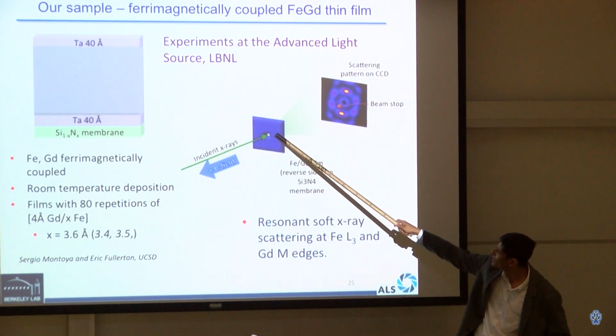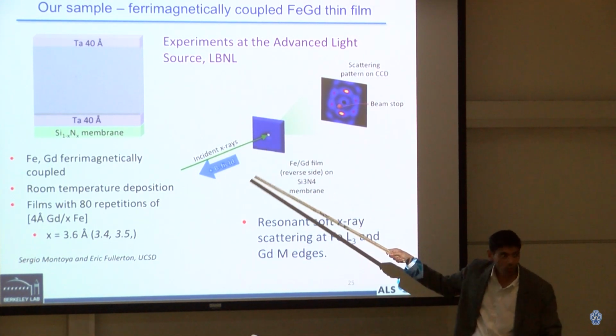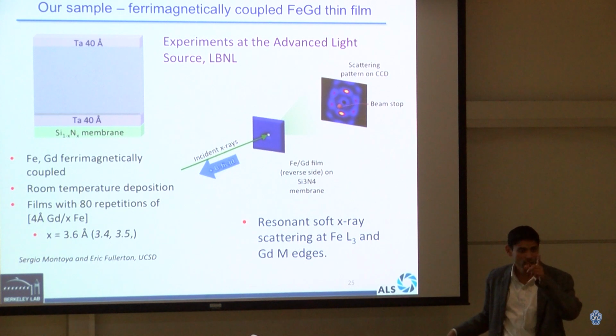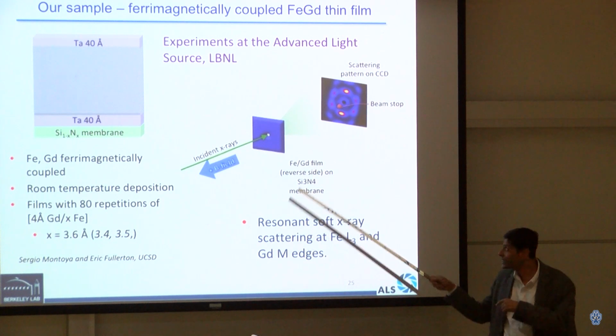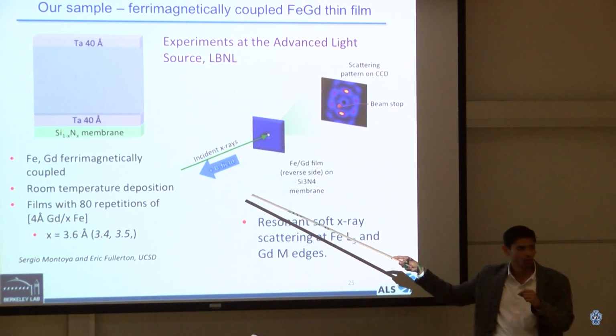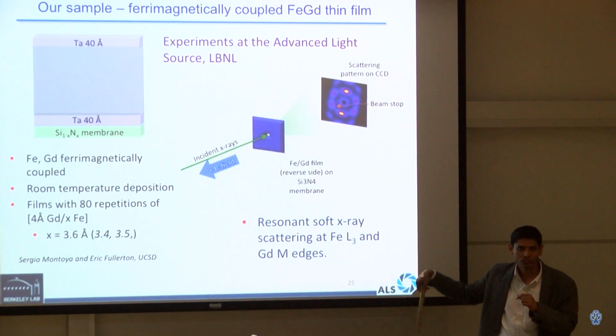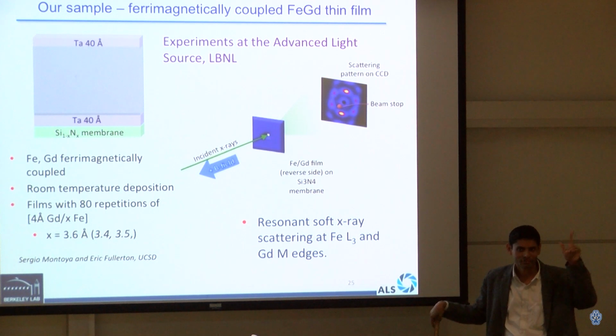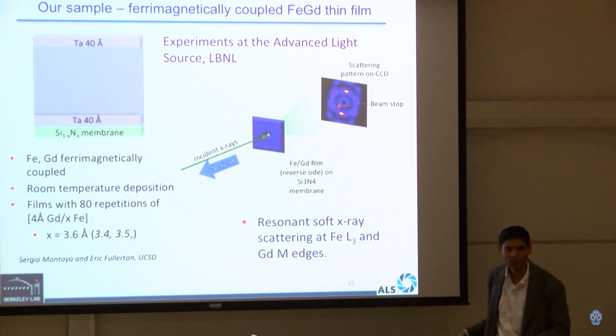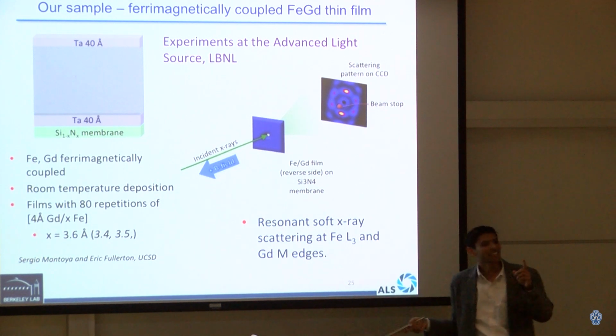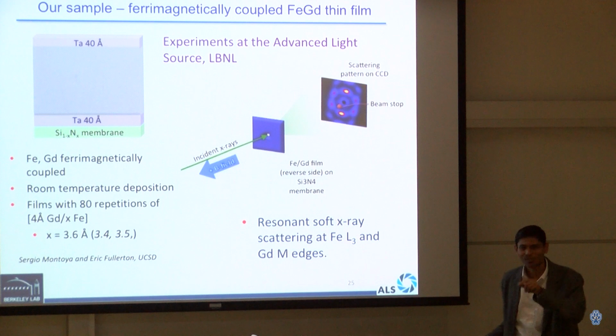So now we have this kind of sample, the beam comes in, now tuned to... anybody paying attention? What is the element we should tune into? For copper selenide, we tuned into copper because it is the magnetic element. In iron gadolinium, where should we tune into? Which one is magnetic, you guess? Iron. Yeah, thank you. So you tune into the iron L3 edge, 707 eV, and you will see a diffraction spot.